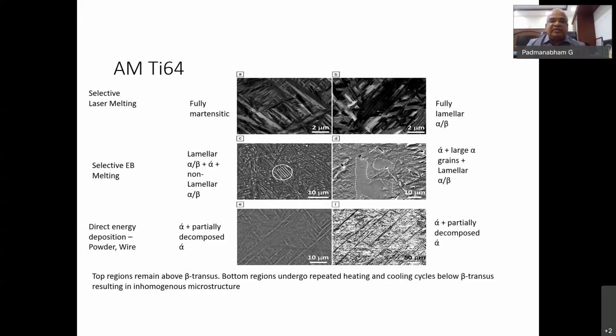top to bottom. There is variation from a fully martensitic structure to a martensite plus partially decomposed martensite, or a combination of lamellar alpha beta. So the top regions remain above beta transus. Bottom regions undergo repeated heating and cooling cycles below the beta transus, resulting in inhomogeneous microstructure. So you can see in this one picture the inhomogeneity in the microstructure you are creating, both from process dependent inhomogeneity as well as the layer to layer inhomogeneity in the Z direction.